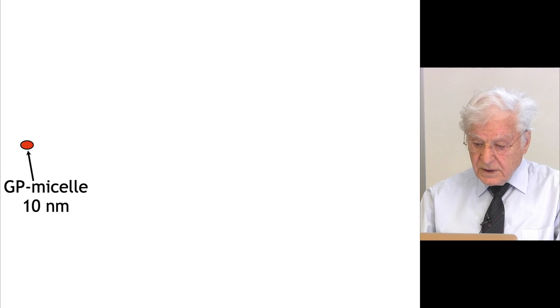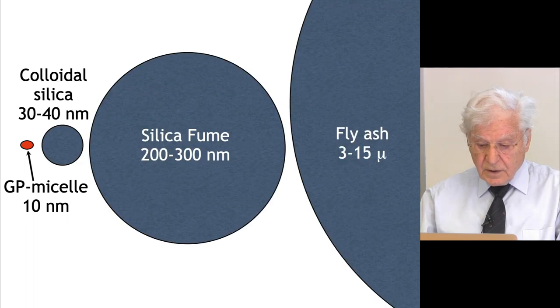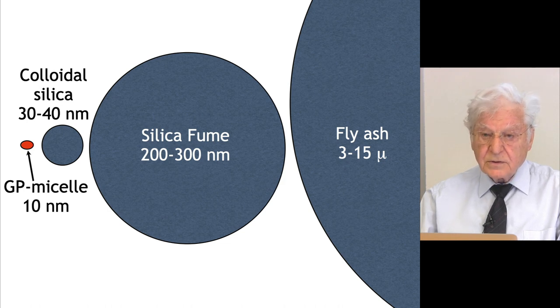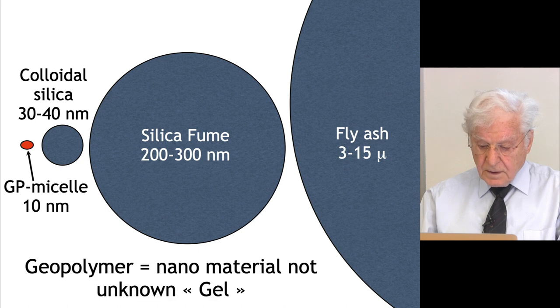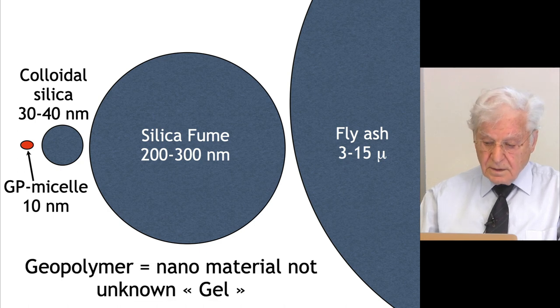The polymeric phase is made of nano and submicron, almost spherical particulates, which we coin geopolymer micelle. The figure shows the very small dimension of the geopolymer micelle, or nanoparticulates, when compared to other spherical structures, colloidal silica, silica fume, and fly ash. Geopolymer is a nanomaterial. It is not an unknown gel.